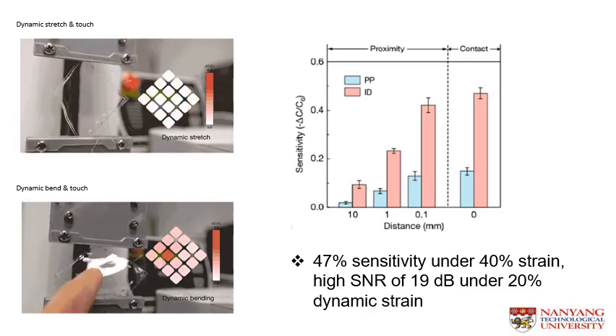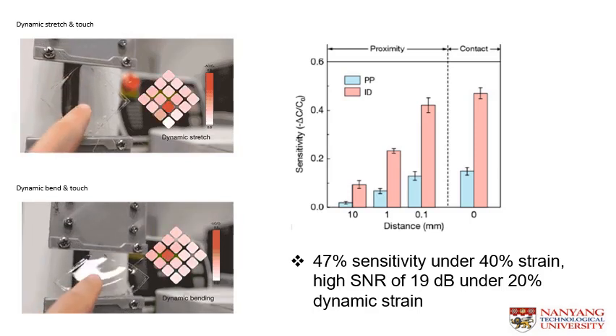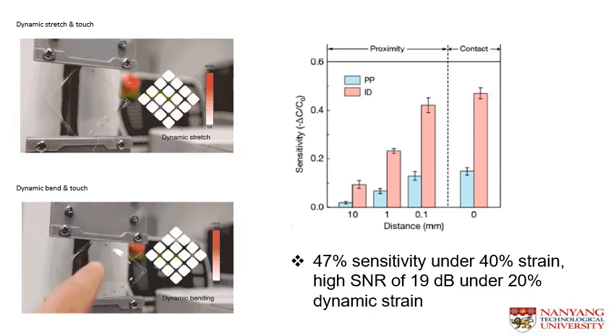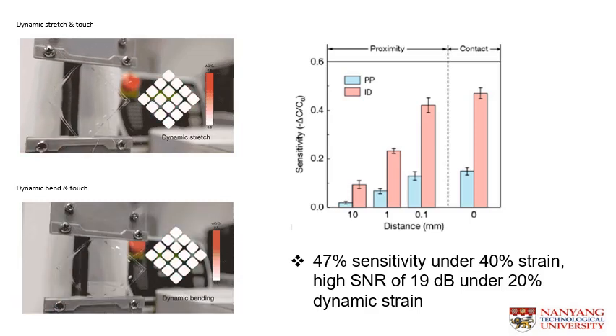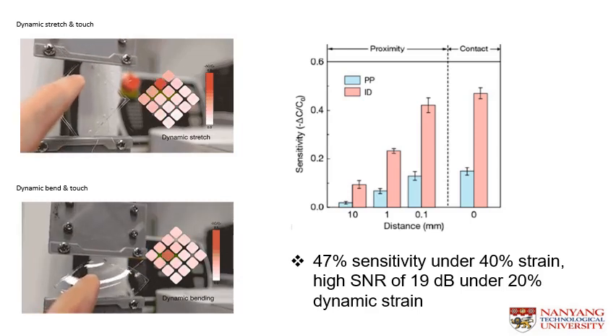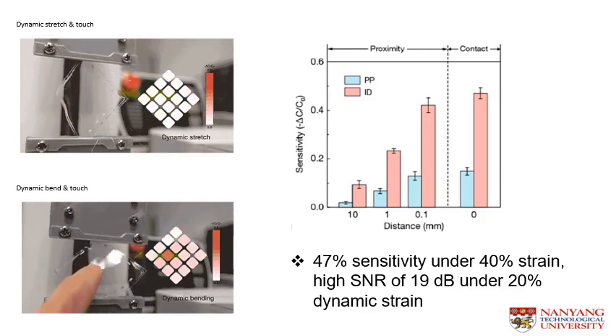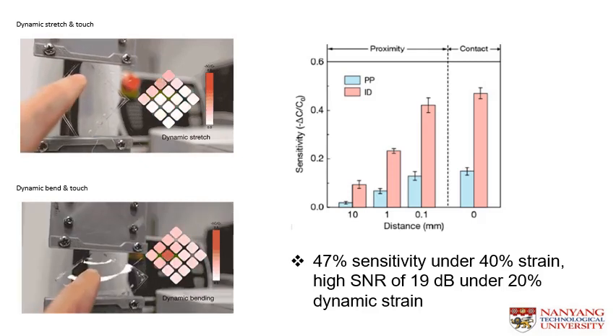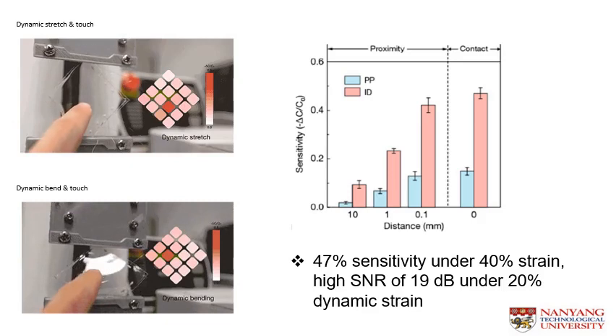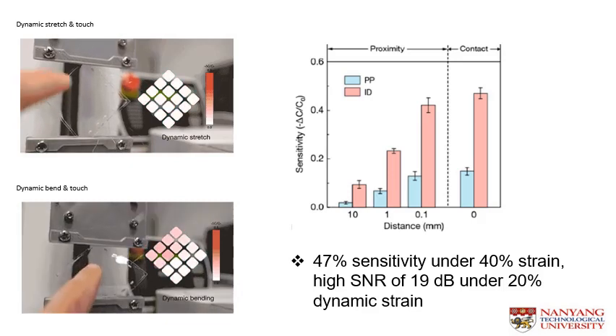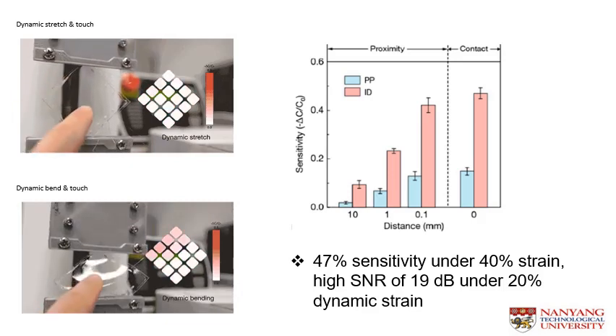It is also working in proximity sensing, as shown in the bar chart, where the interlock diamond layout is providing higher sensitivity. When the touch panel is stretched up to 40% strain, about 47% sensitivity can be achieved. A high signal-to-noise ratio of 19 dB can be achieved under 20% dynamic strain.